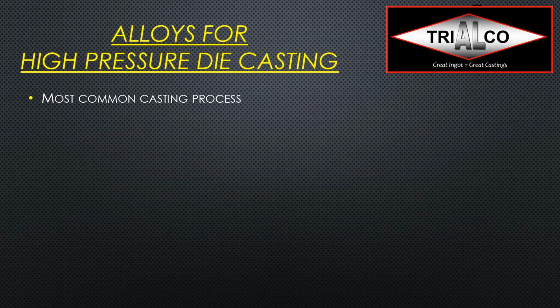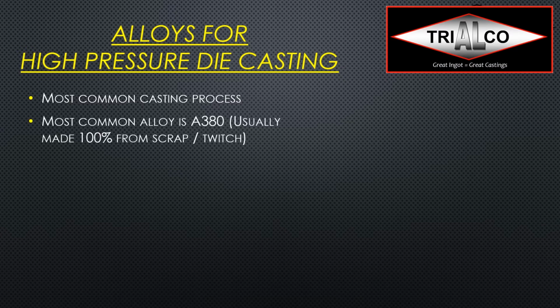So now let's start with alloys for high pressure die casting. It's the biggest consumer of foundry alloys, and it's the most common casting process, especially in North America. And I said it before, the most common alloy is A380, and that is made 100% from scrap. So usually what we call Twitch. So when they shred a car, when they have taken off wheels and heat exchangers and everything you can take off, and it went through a sorting process and pretty much everything that you could recycle otherwise, and the ferrous scrap is taken out and it goes through a shredder, and then what you melt down,